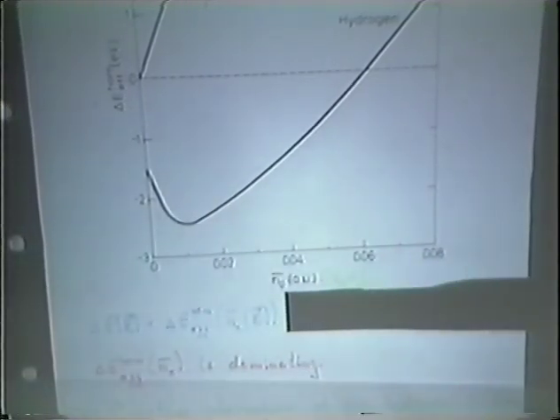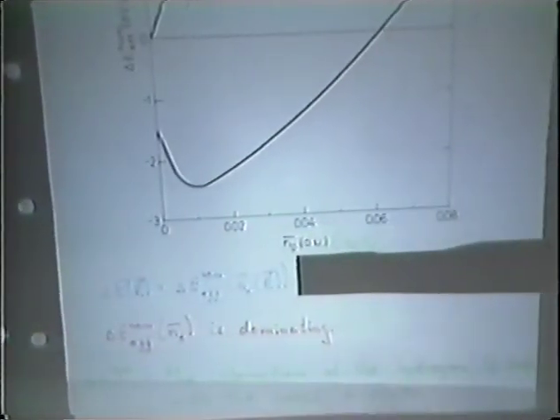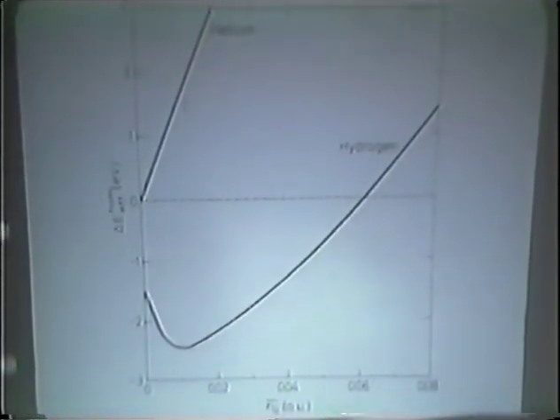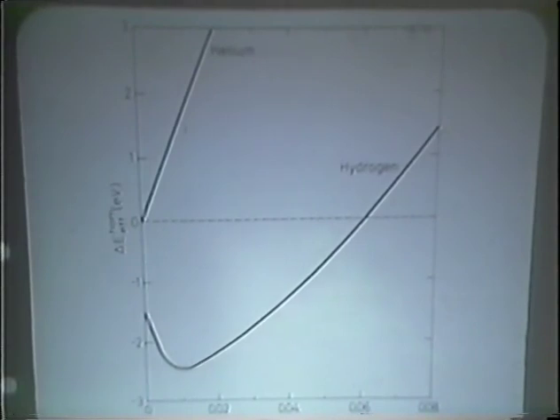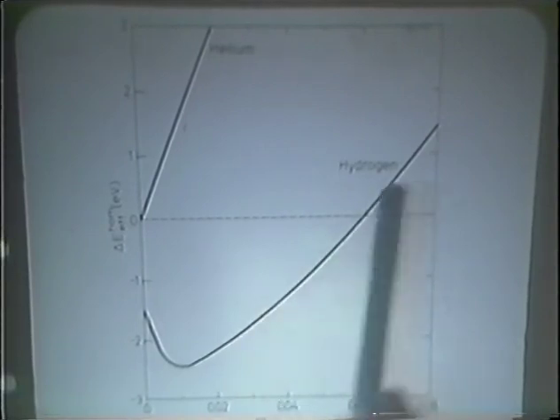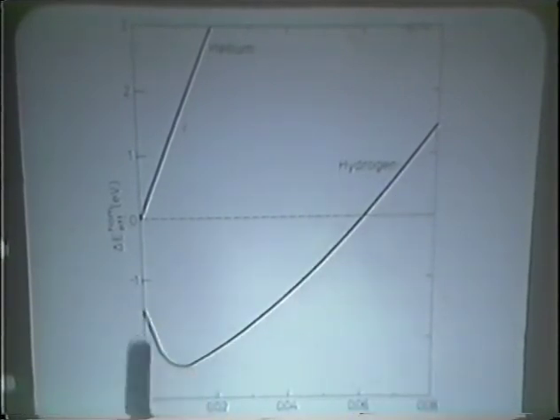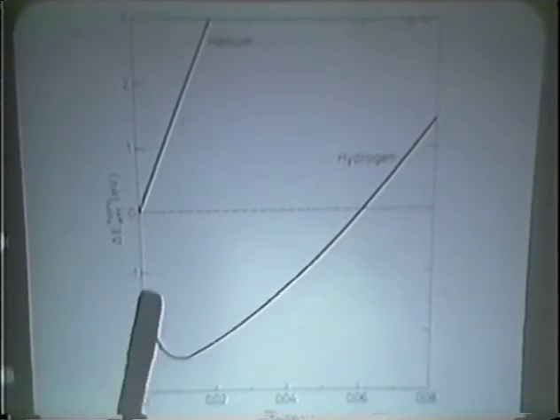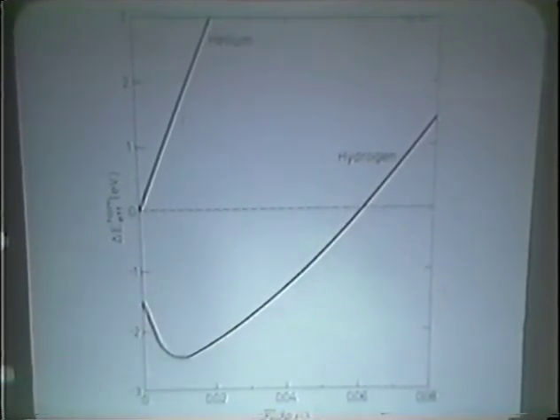If you consider a hydrogen atom coming from infinity and approaching a surface, for example, then it goes through a chemisorption minimum, and then the energy increases as you force the hydrogen atom further and further into the surface. So this increase at higher electron density is nothing else than when you press the hydrogen into a metal atom, then the hydrogen 1s state has to orthogonalize to more and more electron states in the metal, which gives rise to an energy increase. The minimum is explained by the fact that you gain energy by transferring an electron from the electron gas to the affinity level of the hydrogen. It's such a simple curve that you can understand fairly easily.